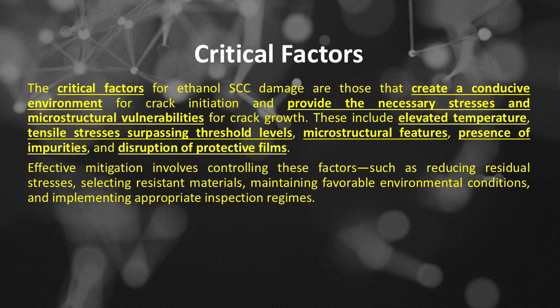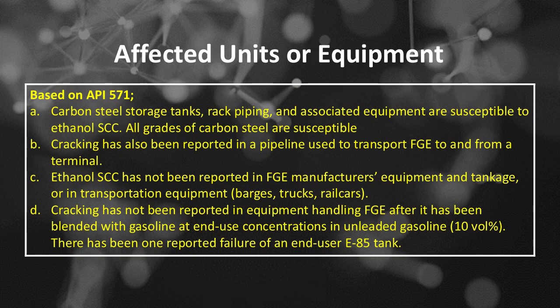appropriate inspection regimes. Ethanol stress corrosion cracking damage, affected units or equipment based on API 571. Number A, carbon steel storage tanks, rack piping, and associated equipment are susceptible to ethanol SCC. All grades of carbon steel are susceptible.